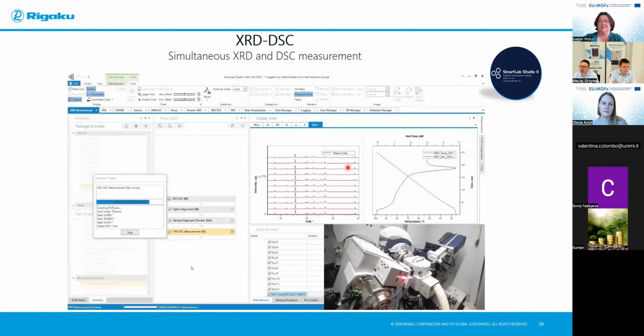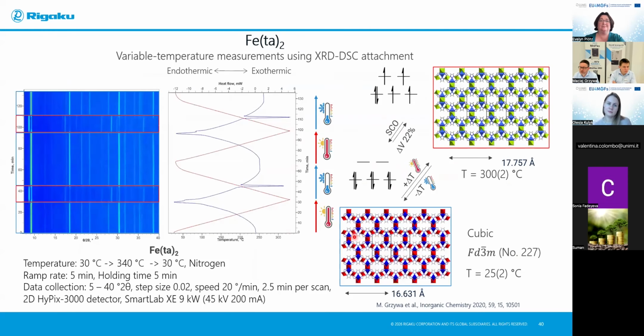And during the data collection in the display area, you can observe simultaneously both the XRD pattern as well as the results from DSC measurement. The iron triazolate shows reversible phase transition. During the heating of the sample, we observe an endothermic effect, and this endothermic effect is connected with the phase transition between the low temperature and high temperature phase.